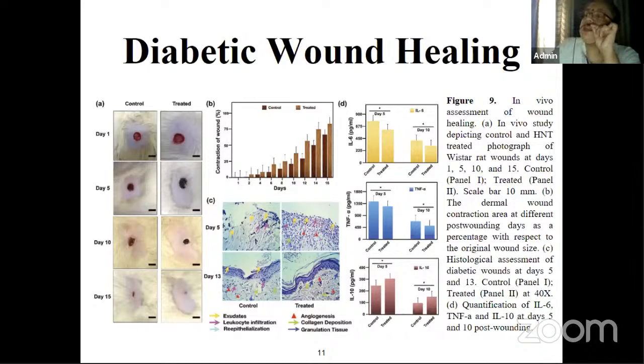However, this nano to micro hierarchical pattern of HNTs plays a profound role in controlling wound moisture, absorbing exudates, space filling, controlling oxygen tension, and wound bed restoration by forming a provisional matrix, as well as painless debridement and preventing loss of water, ingress of microorganisms, specks of dirt, and overall wound dehydration. So wound healing was enhanced in the treated rats with respect to the control because reepithelialization was quicker in the moist environment, which we know hydrogels provide.